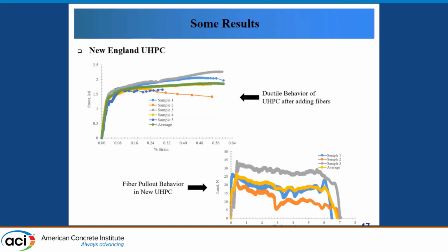Here are some of my preliminary results that I obtained from direct tensile test and the single fiber pull-out test. Both results are very promising. The direct tensile test shows great consistency, strain hardening behavior, tensile strength of up to 2 ksi, and ductile behavior indicated by peak strain of more than 0.5%. The pull-out results show high load resistance and shear strength hardening. This is seen by keeping the pull-out load almost constant, although the fiber is being pulled out and thus steadily reducing its embedment length. We are in the process of doing more tests in the future.